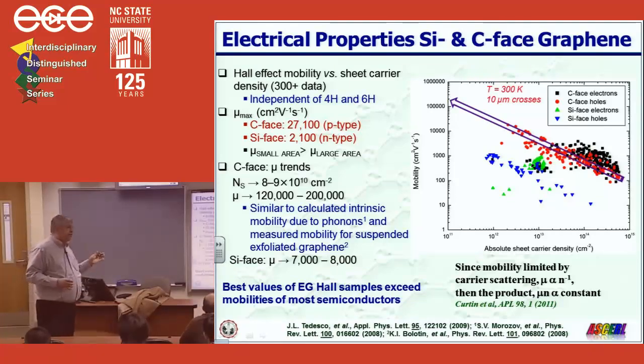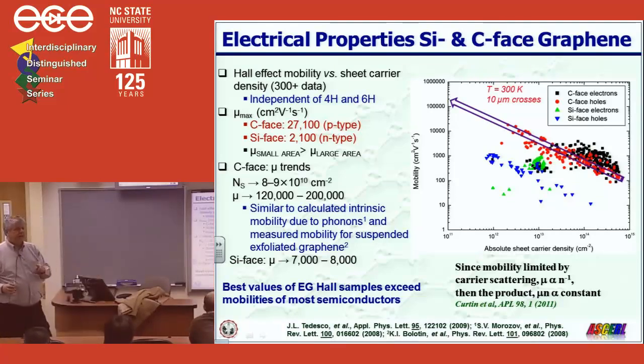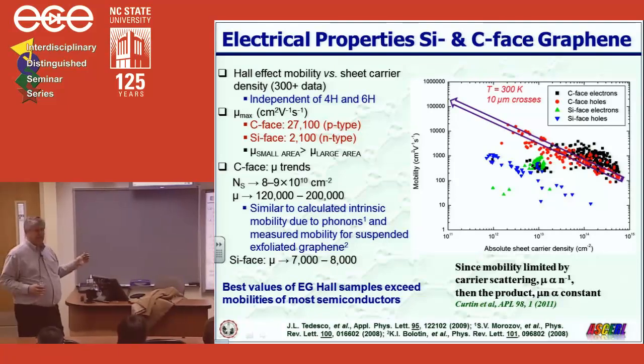The other message to take home is, if we look at the sum total of the carbon face data and extrapolate it to the intrinsic charge density that you would expect for graphene at room temperature, you would expect a mobility on the order of 200,000. That is exactly the value that you get for suspended graphene. So this is the same graphene. It's behaving exactly the same. It's just that it's sitting on another surface.